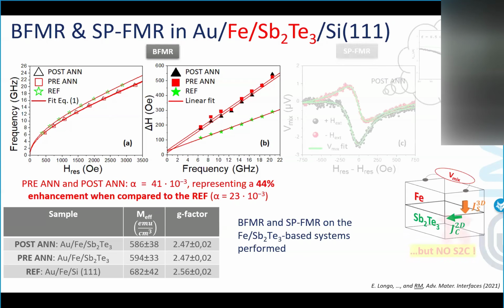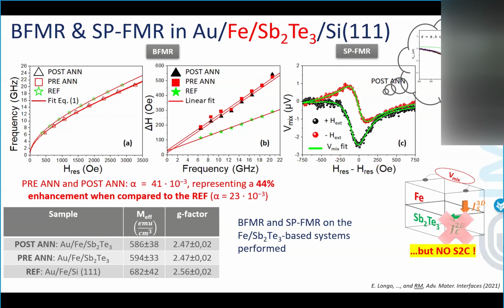I will not give details, but just point attention here that the slope for the samples on top of the topological insulator jumps up when compared to the reference. This is connected to the damping effect that you have in FMR, and very often in the literature, this is attributed to a spin pumping process, so an efficient spin charge conversion. But if you do it electrically, which we have done, we do not see any electrically detected spin charge conversion, even if by Mössbauer we were able to get a pure interface. Because in this case, you would expect, when you reverse the magnetic field here, that the symmetric part jumps reverse exactly, while this doesn't happen. So Mössbauer spectroscopy was very helpful to say this is not enough, so you must do something else.